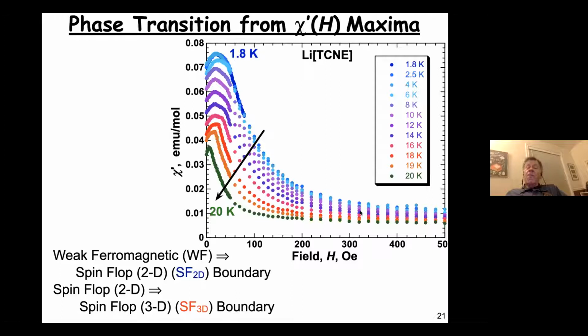We can also look at the maximum in chi prime of H as a function of temperature. And you can see at 1.8 Kelvin over here, it's fairly broad, suggestive of 2 maxima. And as you go down and up in temperature, the intensity drops, and it looks more like there's only 1 peak in there. And as a consequence, we can see a phase transition. And we've now analyzed this, which we'll talk about in a couple minutes, as having 2 transitions, one from the weak ferromagnetic phase to a spin flop in 2 dimensions, and then at slightly higher field going from the spin flop in 2 dimensions to a spin flop in 3 dimensions, designated SF2D and SF3D for this material.